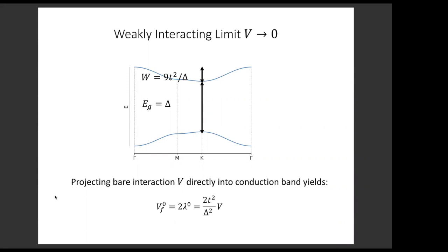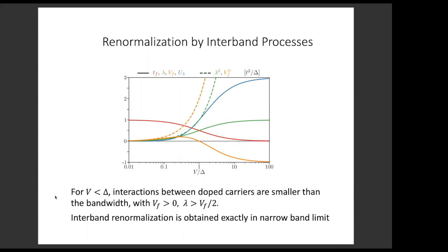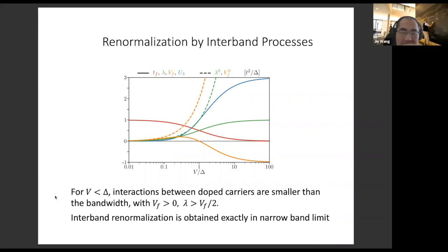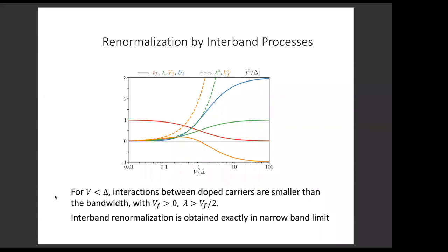However, next slide. If we go beyond this small V limit, what this plot shows is the interaction strength of the interaction V over delta. So the x-axis is on the log scale. The dashed line is what you would obtain if you just do the direct projection into the conduction band without taking into account virtual interband processes. While the solid line is what we obtain exactly from this Schrieffer-Wolff transformation. That is exact in the narrow band limit. And you see that